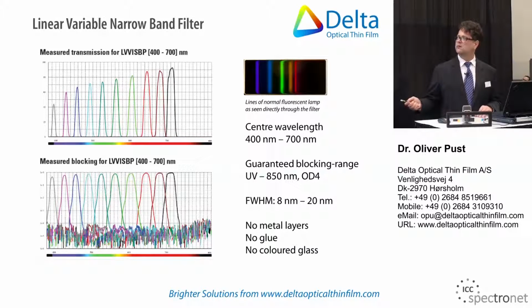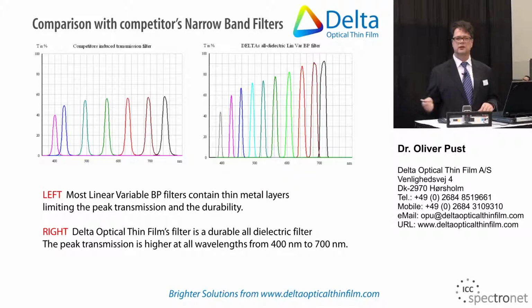Once more, a comparison with older technology. On the left-hand side, you see a so-called induced transmission filter that uses thin metal layers. That on one hand limits your peak transmission, but it also renders the filter impossible for laser applications. It will absorb the laser energy and simply burn. And again, on the right-hand side, our filter, with much steeper edges and much higher transmission at any given wavelength than previous technology.